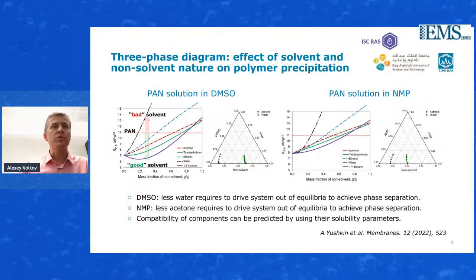What I'd like to show here, on the left graph, is that if we have a Hansen solubility parameter distance lower than that of PAN, it means that we have a mixture of polymer and solvent which forms one phase. And once we increase the other component in the polymeric solution, we have a phase transition into two phases. So that means that we have a bad solvent or something like that. And indeed, considering two solvents, DMSO and NMP, we can see that less water is required to go through the threshold value 1. So that means that we have the precipitation.